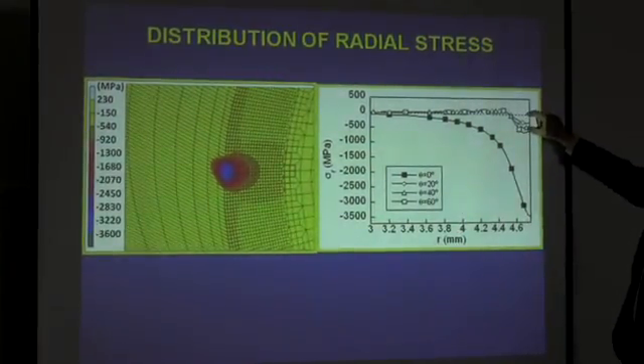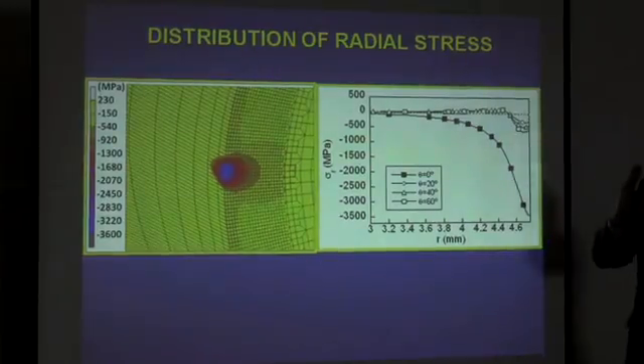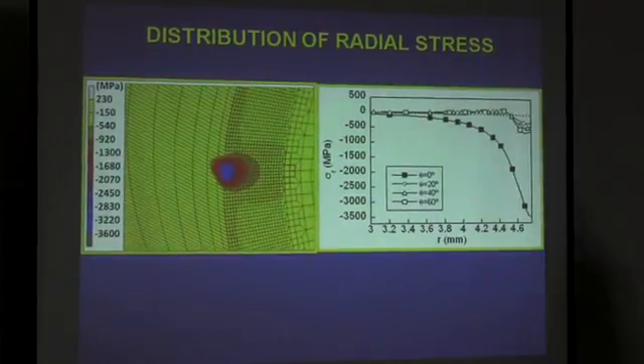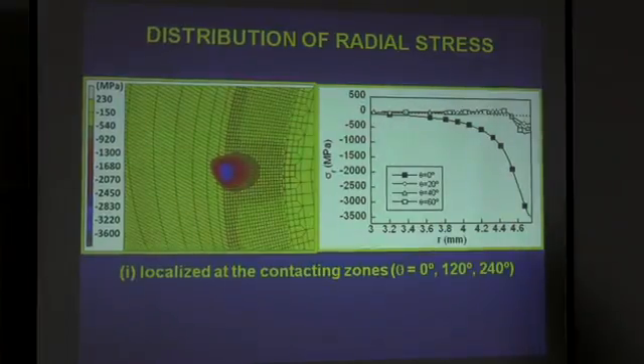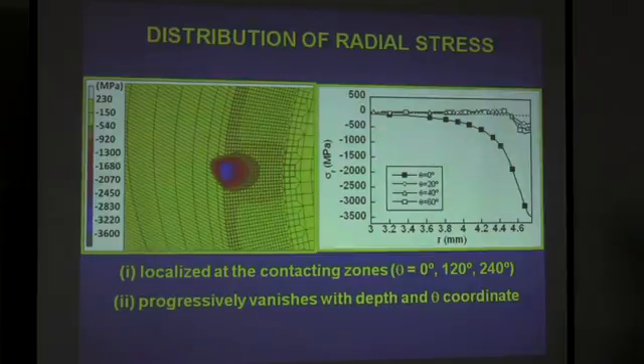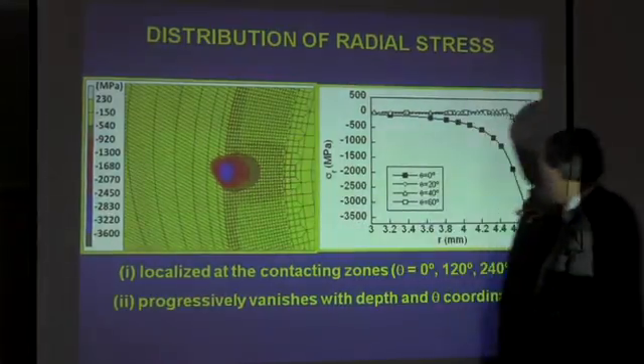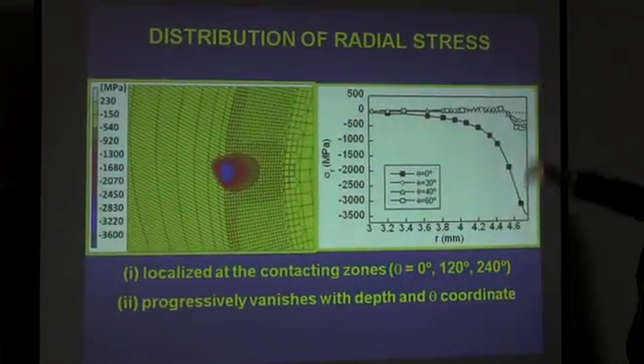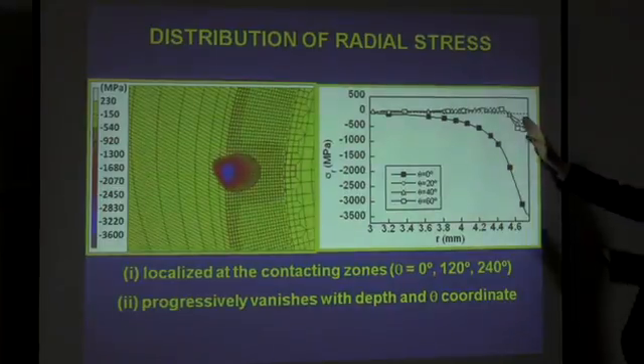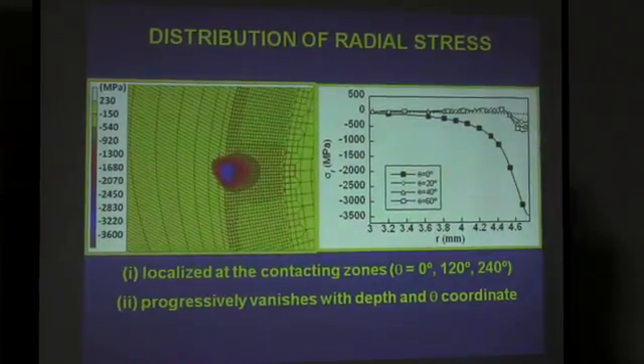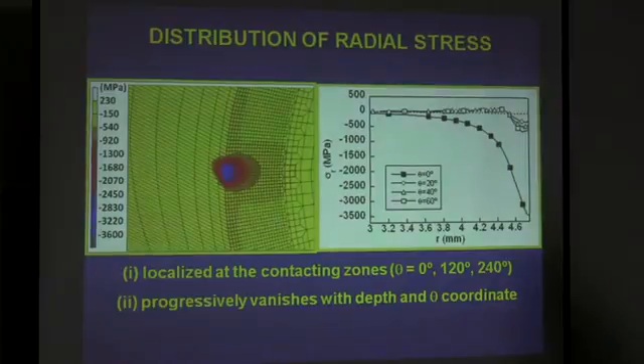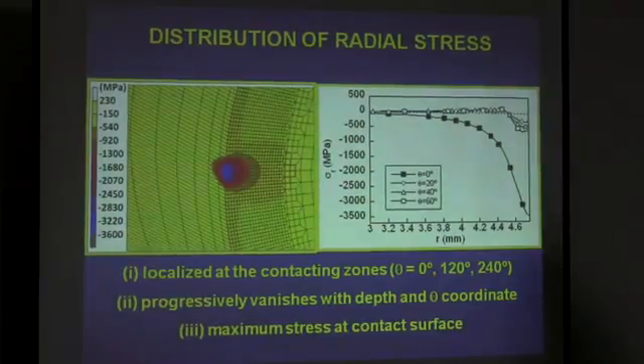With different angles, the concentration of stress is relaxed as the angle increases from the θ0, which is the contact plane. Then we have localized radial stress at the contacting zone, 0, 120 and 240, symmetry, 3 planes of symmetry, progressively vanishes with depth, of course, the depth from the contact here vanishes. This is the maximum concentration, negative stress, and with the θ coordinate as we depart from the contact plane, and maximum stress at contact surface.